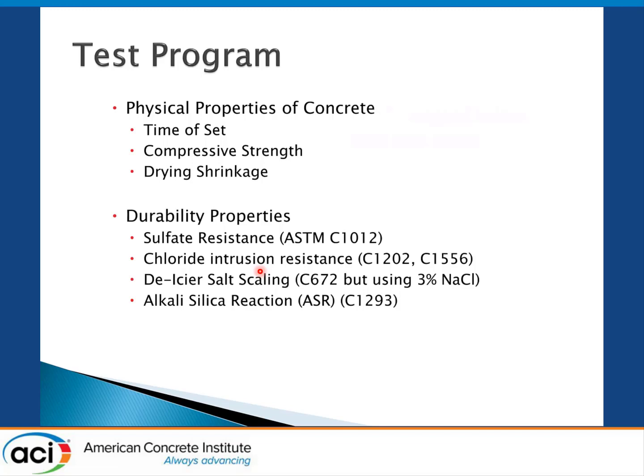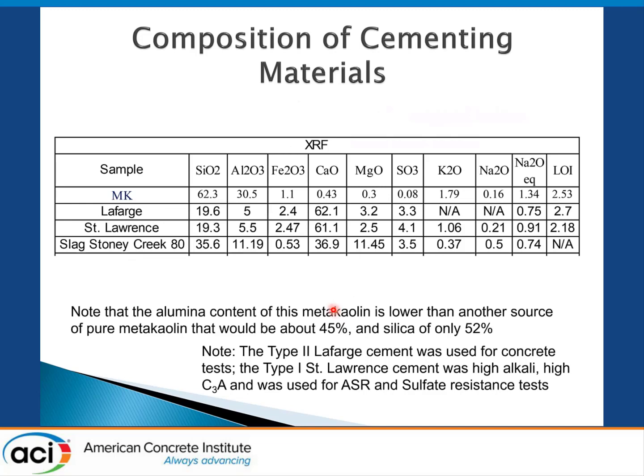The test program we did at the time measured physical properties of concrete and also a bunch of durability properties, including sulfate resistance, chloride resistance, de-icer scaling, and alkali-silica reaction. Now, the sample we have, you can tell it's not pure because it's only about 30% alumina, whereas a pure, fairly high-grade metakaolin that we've done research on earlier has about 45% alumina.